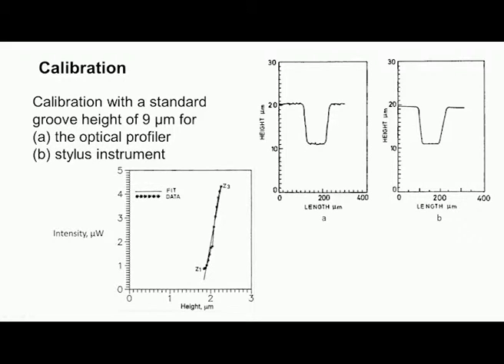Now, it is very essential that before using such a system, we have to calibrate the system. Here we can see the calibration is carried out using a standard groove with a groove height of 9 micrometer. This is the calibration result obtained by the optical profiler, and this is the calibration curve obtained by the stylus instrument. Now, we know that the groove size is 9 micrometer. After measuring that groove, you can see here this depth is 9 micrometer. Similarly, in the stylus type instrument, this is approximately equal to 9. So, there is a small amount of error here.